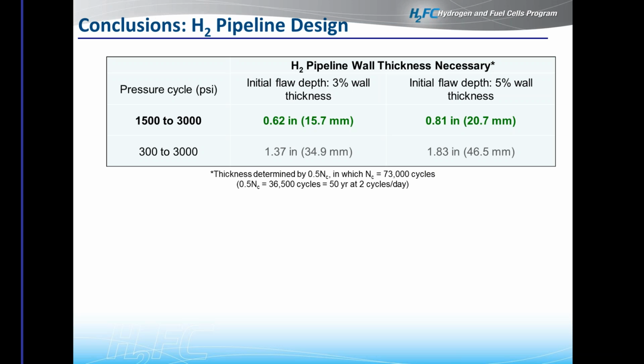And so what that tells us is, based on these calculations in fracture mechanics, the necessary minimum wall thickness to sustain pressure cycles that range from 3,000 to 1,500, and at a crack in the wall that is 3% of the wall thickness, we need a thickness of pipe that is 0.62 inches. As we have a slightly higher flaw depth to begin with, that increases our necessary wall thickness up to 0.81 inches.